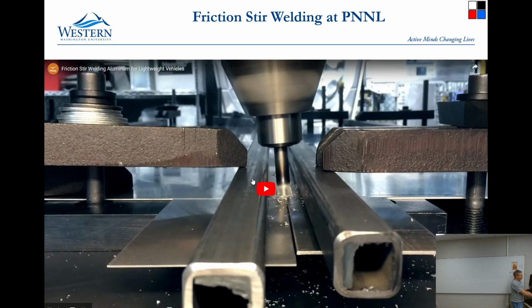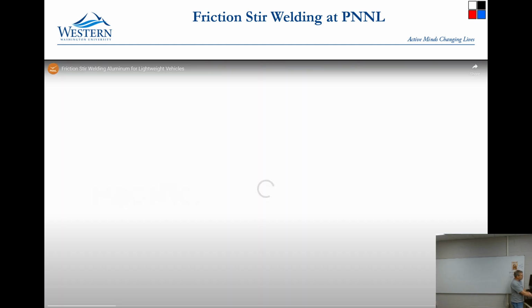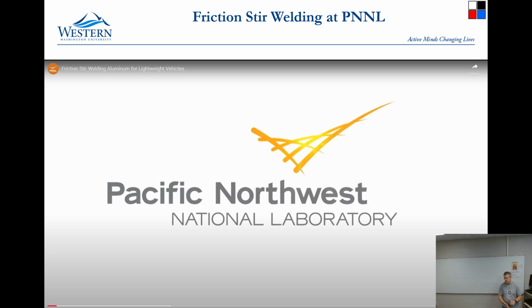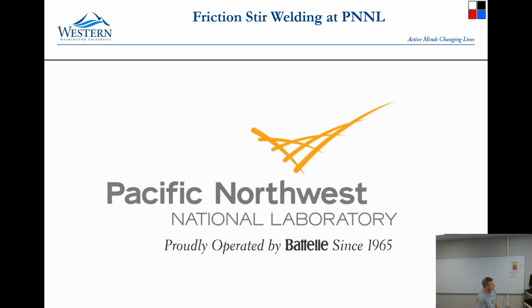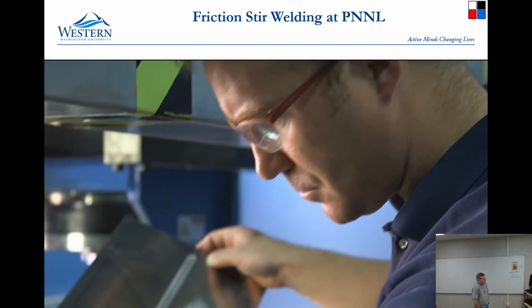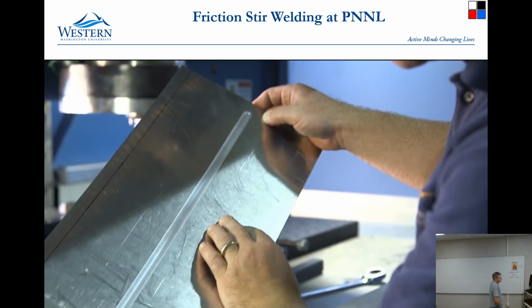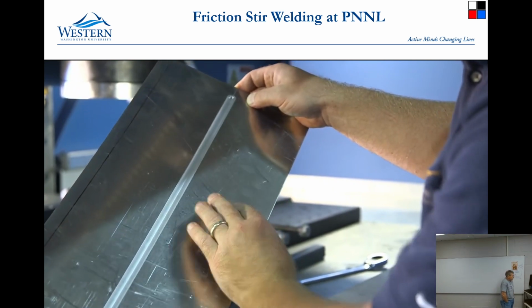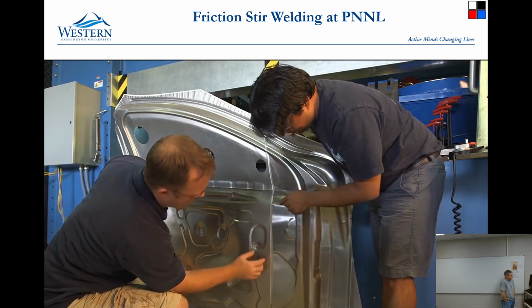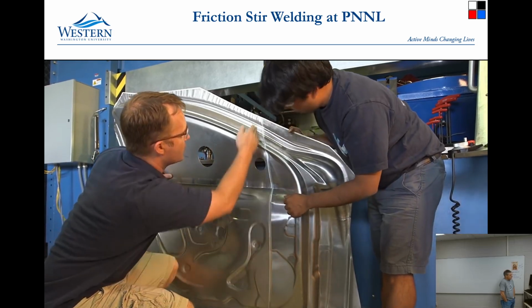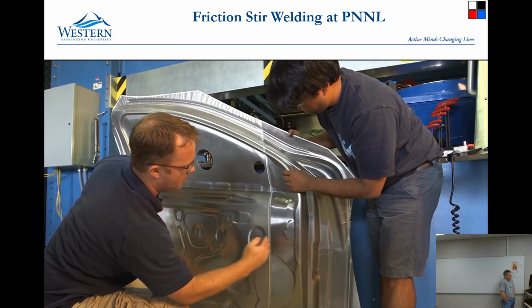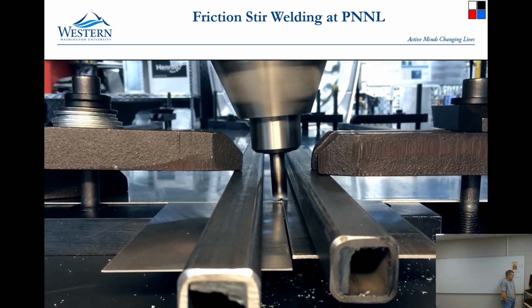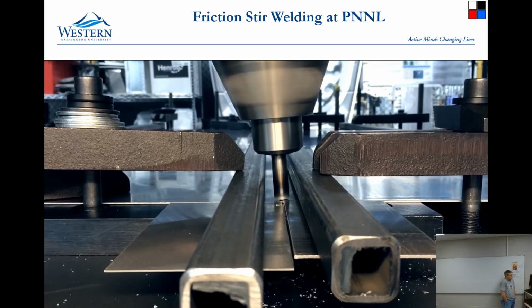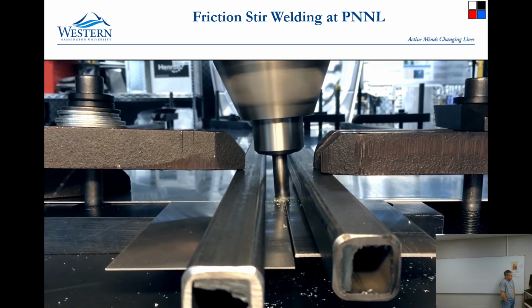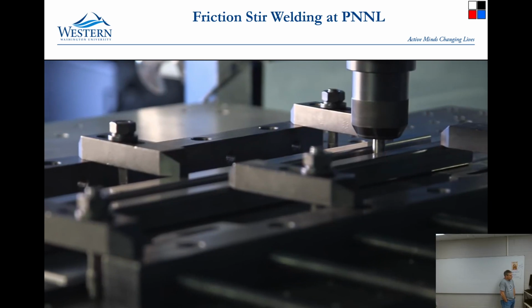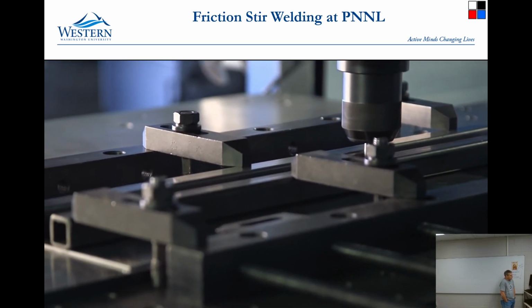This is how friction stir welding works. One of the challenges to more widespread use of aluminum in automobile construction is joining. Friction stir welding is a process that allows us to join two materials together without ever melting them. We use a tool which is rotated and plunged into the interface of two abutting plates and then stirred down that interface in order to locally forge the materials together.